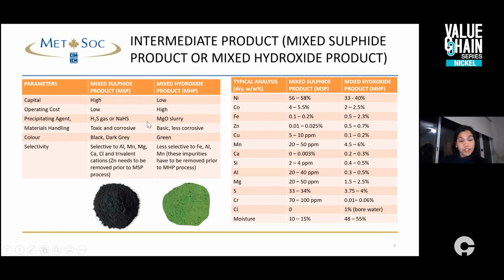In contrast, the operating cost for mixed sulfide is low, and for mixed hydroxide it is relatively high because of the high cost of MgO. As I have mentioned, for mixed sulfide, the precipitating agent is either H2S gas or NaSH. For MHP, it's MgO slurry. So this is a typical mixed sulfide product. It's dark gray to black in color, while mixed hydroxide is a green precipitate.